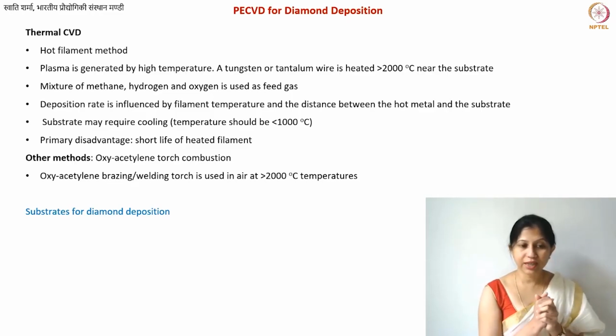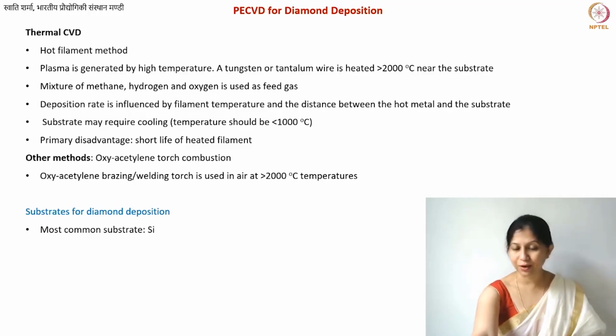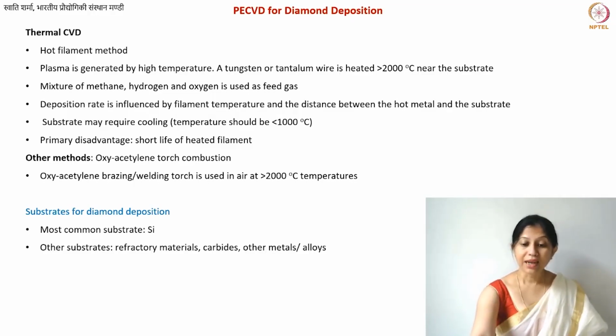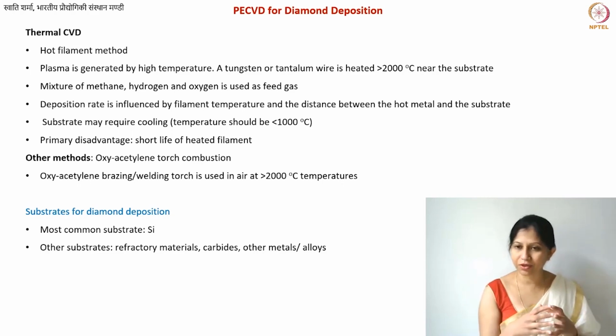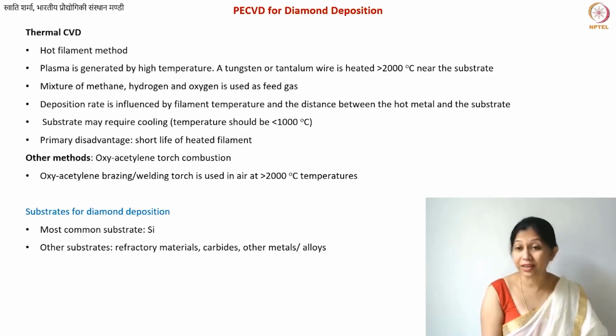So what are the substrates? As I already mentioned, substrates do not need anything too special, so they are not performing the role of catalyst in this particular case. The most common substrate for these films is silicon, but often we require coating of these diamond films on different parts, for example automobile parts or other parts. So you can even use the entire part as your substrate. You can also use various refractory materials, and graphite itself can be used in that case. Various carbides can be used, and other metals and alloys. As such, we are not too particular about the substrate when it comes to diamond CVD.